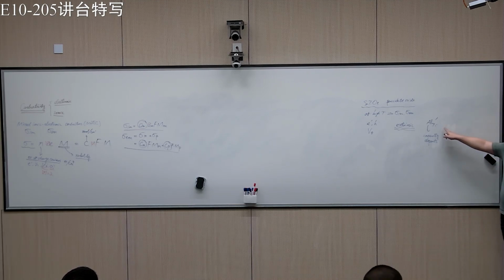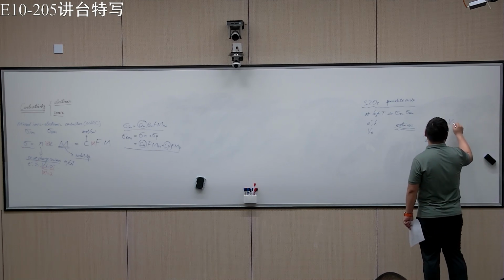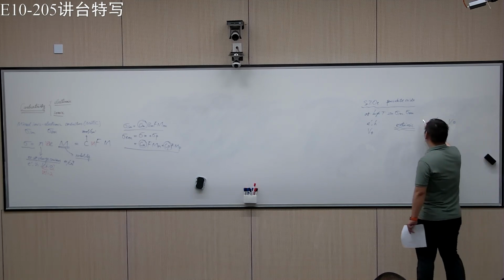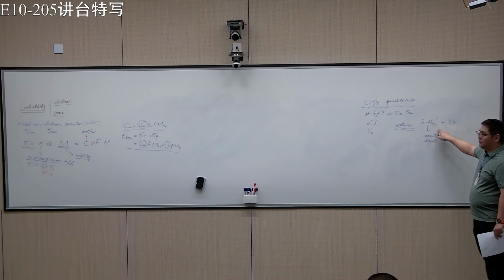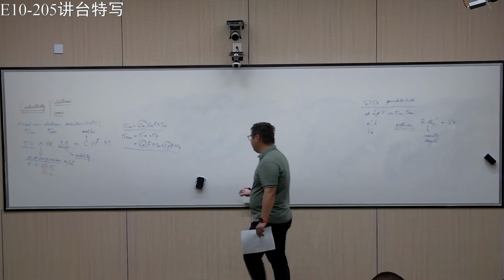So if we dope the system with this negative charge defect, there has to be something positive for charge balancing. It turns out that for charge balancing, we have oxygen vacancies. Of course, to have charge neutrality, it has to be two to one for the stoichiometry.